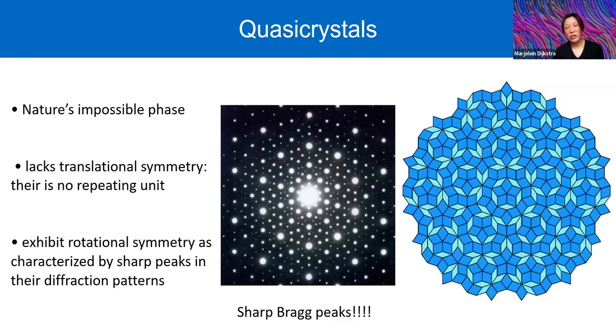So we chose a system which is actually a quasicrystal. Quasicrystals are also called nature's impossible phase. It lacks translational symmetry, so there is no repeated unit. It's not like a crystal where if you know the unit cell and you are sitting on top of an atom, you know exactly where all the other atoms are. But if you take a diffraction pattern of such a quasicrystal, it shows very sharp Bragg peaks, but with a rotational symmetry that is forbidden for crystals.